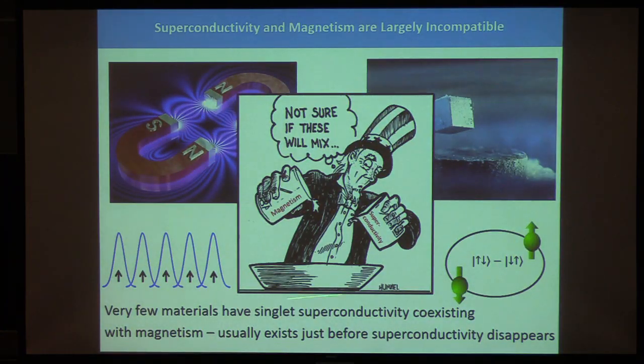Now, it's not hard to see that magnetism and superconductivity are incompatible. Superconductivity wants the spins to be opposite one another, and it's not enough that it's an antiferromagnet where there is time reversal symmetry broken. This really wants to be a time reversal symmetric state, whereas magnetism, for example, the ferromagnet, wants the spins to be aligned. So these two states don't mix together, and in fact, the only place where there are some experimental indications of seeing coexistence of ferromagnetism and conventional superconductivity is usually just before superconductivity goes away.